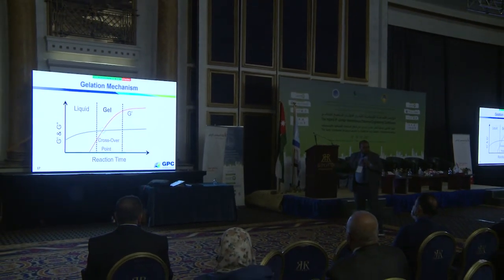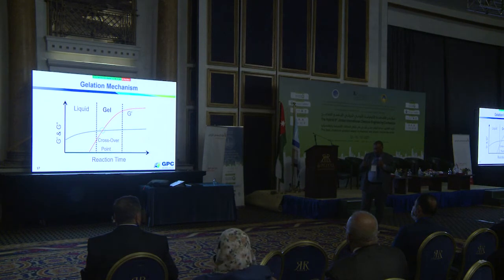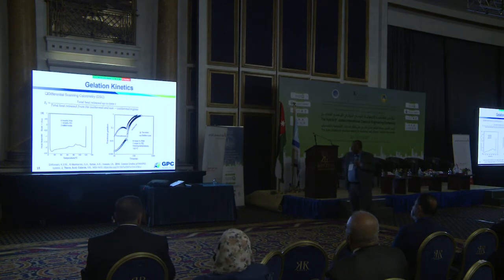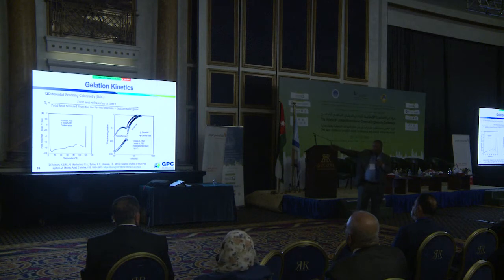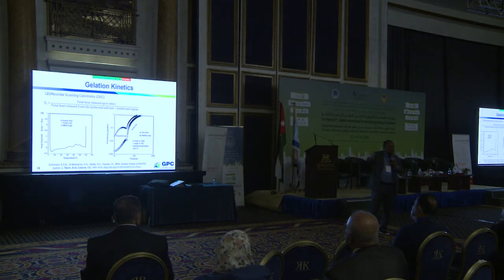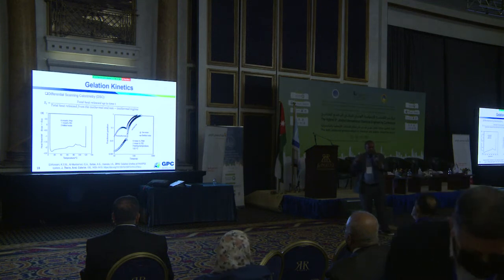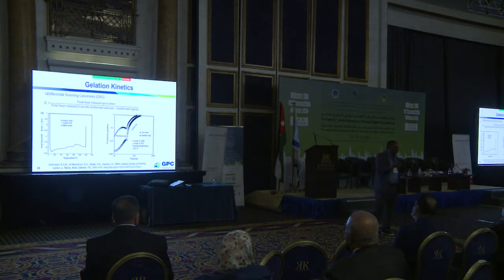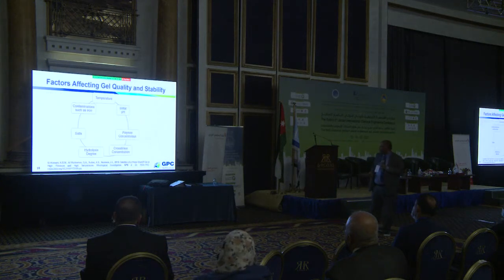We don't want G prime to be like a solid, because otherwise we cannot inject it. So the gelation mechanism should be studied carefully. Here I'm going to talk about it rheologically and through thermal analysis. We can study what we call rheokinetics, or we can study the kinetics through thermal analysis and understand the mechanism, play with the formulation, and sometimes delay the gelation using different chemicals, so play with the chemistry to avoid any gelation during injection. Of course, the gel and gel strength are affected by so many factors.